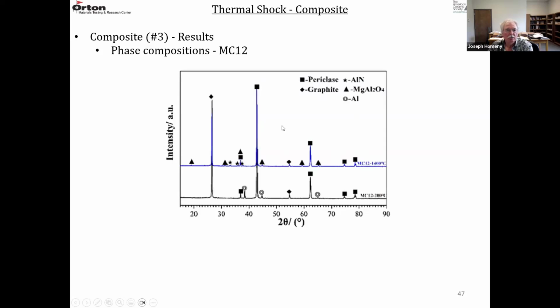And then the MC12 is basically the same, primarily periclase and graphite at either curing temperature, some aluminum metal at 200 degrees C curing, and then you're going to get a little aluminum nitride and spinel at the 1400 degrees C curing.